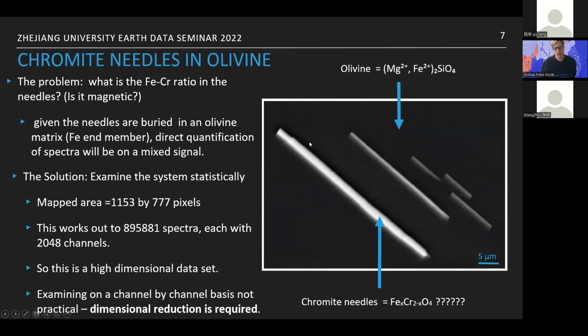And this is a very difficult measurement. Traditionally for electron microprobe or standard EDS in an SEM, because what ends up happening is due to the interaction volume, the signal for the needle gets convoluted with the signal from the olivine. And so figuring out that exact ratio is very difficult. So the solution we present, and the way that we're going to proceed with a lot of the rest of the analysis in this talk, is we take it as a statistics problem.